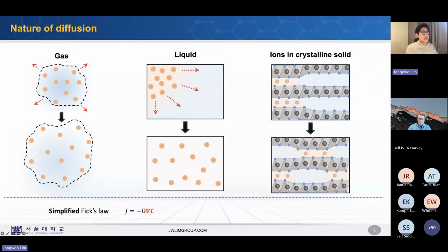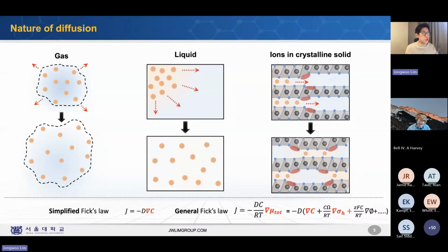However, in the solid system, when the lithium diffuses within the cathode particle along the channels, it is not only driven by the concentration gradient, but also faces many strain effects. In fact, the general Fick's law we teach in grad school courses says that diffusion is actually driven by the chemical potential gradient, not simply by the concentration gradient. There are additional factors: concentration gradient, strain and stress level, mixing entropy, interfacial energy, and so on. So basically, diffusion within the solid state has to follow the chemical potential gradient, not just the concentration gradient.